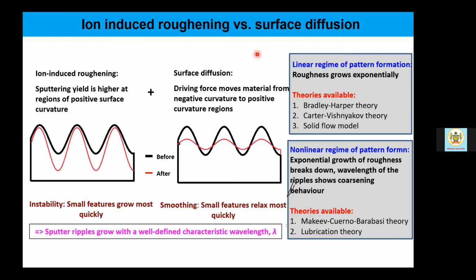There are several theories available to understand how roughness evolves. And there are two regimes. At very high ion fluences, nonlinear regimes of pattern formation come into the picture. Otherwise, in the linear regime, the pattern formed in the linear regime means roughness grows exponentially. And several established theories like Bradley-Harper theory, Carter-Vishnyakov theory, and the solid flow model can be stepping in. And for the nonlinear regime of pattern formation, exponential growth of roughness breaks down. Wavelength of the ripple shows coarsening. And Makeev-Cuerno-Barabasi theory or lubrication theory take well care of pattern formation in those regimes.